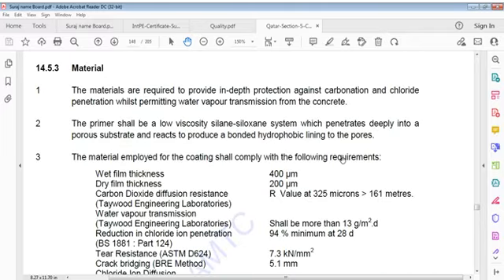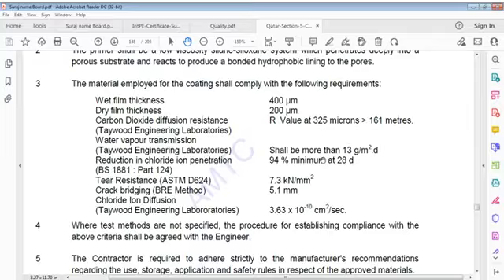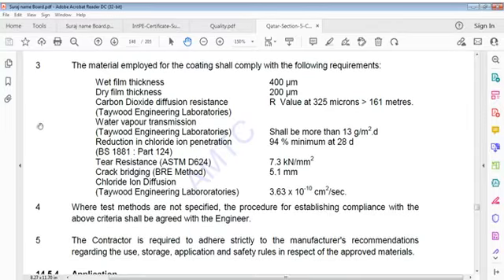Materials are required to provide in-depth protection against carbonation and chloride penetration, whilst permitting water vapor transmission from the concrete. The primer shall be a low viscosity silane siloxane system which penetrates deeply into the porous substrate and reacts to produce a bonded hydrophobic lining to the pores. Materials employed for coating shall comply with the following requirements. Wet film thickness WFT is 400 micrometer, 400 into 10 to the power minus 6 meter, so 0.0004 meter. Dry film thickness is 200 micrometer.